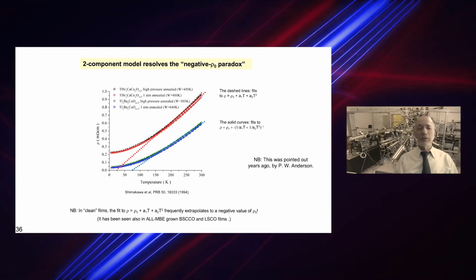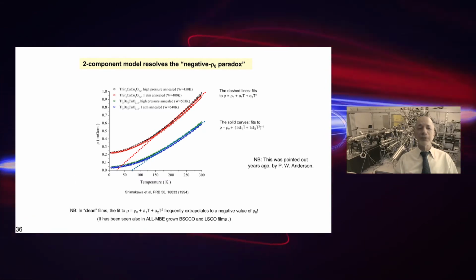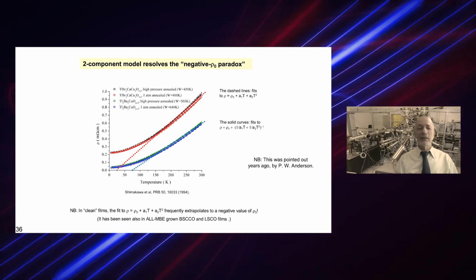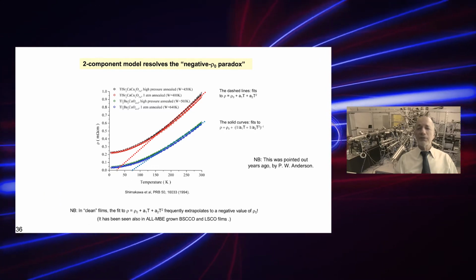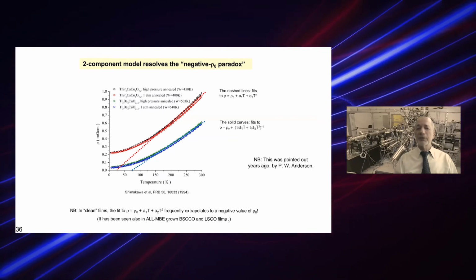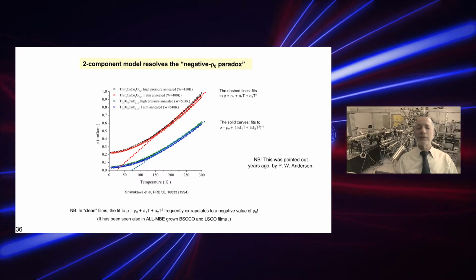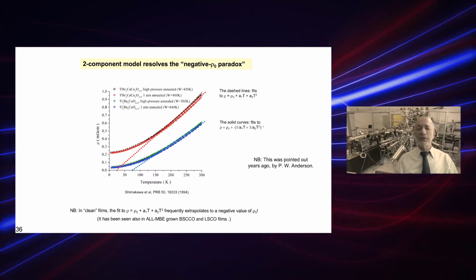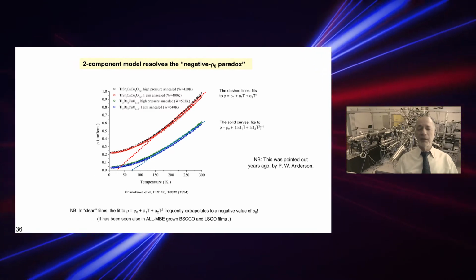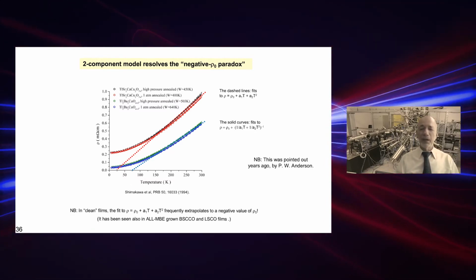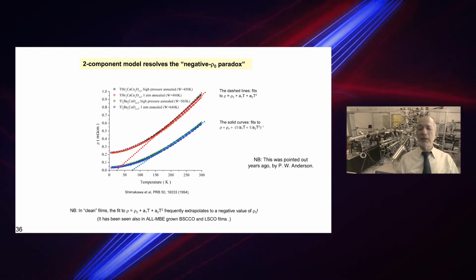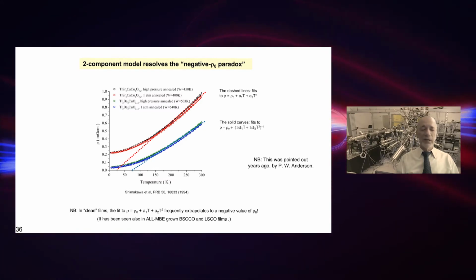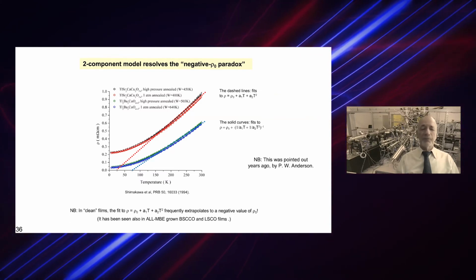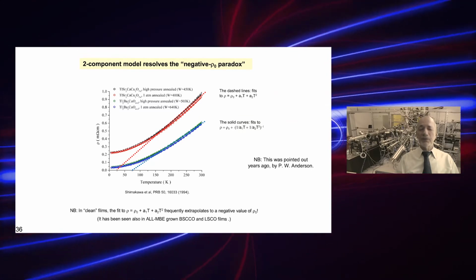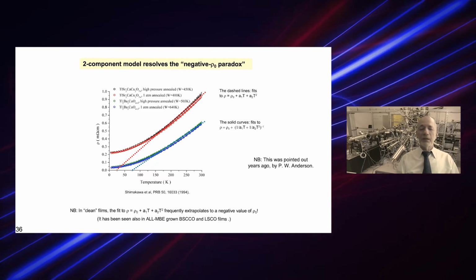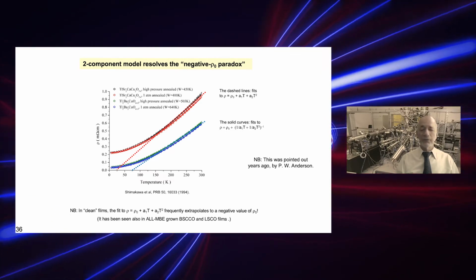I want to focus on this data for thallium strontium calcium cuprate, which is very clean. And here you can see something even stranger. If you fit to the series resistance model, you simply extrapolate the high temperature linear in temperature resistivity part down to zero, you will get a negative intercept. And this, of course, makes no sense. But you can actually fit this very well to a parallel conduction model, in which case the paradox goes away. And this seems to be seen also in other samples once they're very clean. So I've seen this in a number of BSCCO films and also in a few LSCO films.